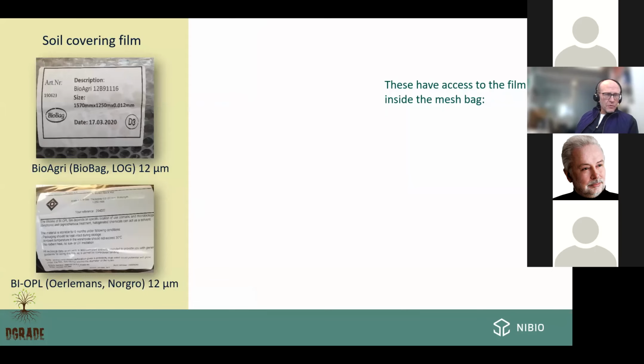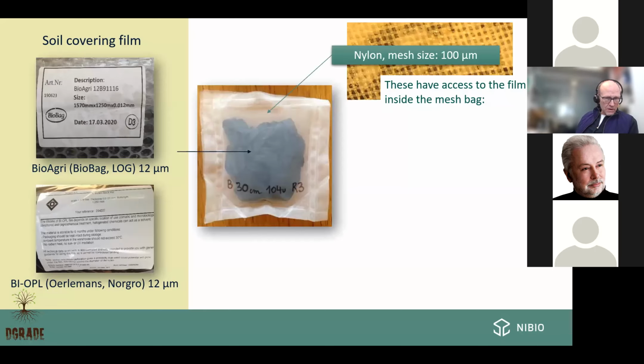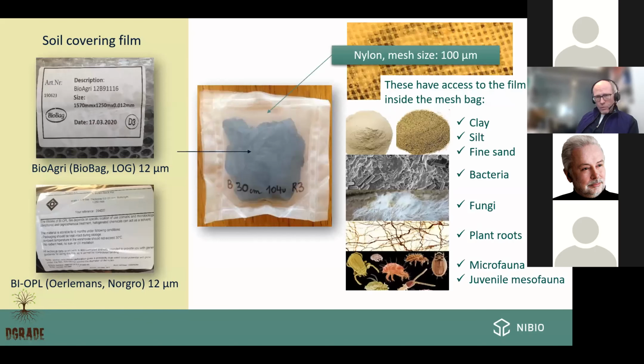The materials we used were the two main biodegradable films available in Norway when we started, one from BioBag and one from Oerlemans, both at 12 micron thickness, and we enclosed them in these nylon mesh bags, packing a 20 by 20 centimeter square into a small ball and welding the nylon mesh bag to contain it. We have tested this and can see that all these materials listed to the right can enter into the mesh bags: soil materials like clay, silt, and fine sand, bacteria, fungi, plant roots, and small soil animals, microfauna, and juvenile mesofauna.